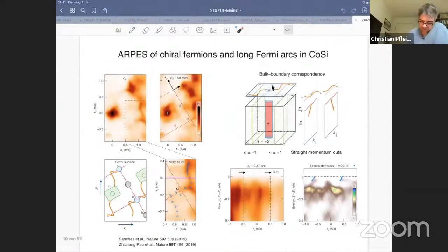And indeed, there are two papers back to back in 2019 carried out on cobalt silicon, right? They were reporting ARPES measurements. Actually, part of the trick to do these measurements was very skillful preparation of the samples, because the cobalt silicon, even though it can be prepared very nicely as a bulk sample, it's very difficult to get a really nice surface. So they sputtered surfaces basically onto single crystals, and then annealed them very carefully to have the appropriate quality for ARPES measurements.